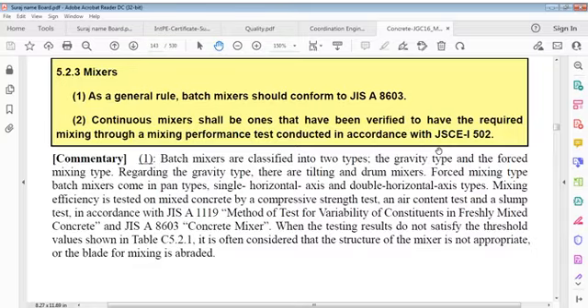Mixing efficiency is tested on mixed concrete by a compressive strength test, an air content test, and a slump test. Methods of test for variability of constituents in freshly mixed concrete. For concrete mixers, when testing results do not satisfy threshold values, it's often considered that the structure of the mixer is not appropriate or the blade for mixing is abraded.